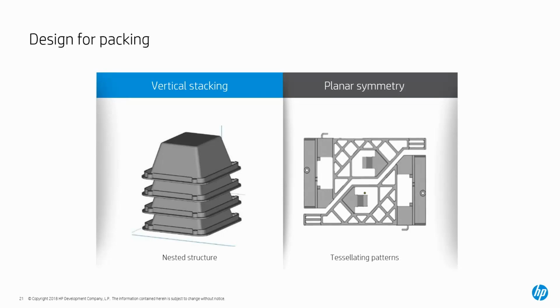in addition to the fact that it allows you to nest a little bit better inside the parts. One other process that we used was vertical stacking, or solo cupping. So typically this filter housing that you would see on the left-hand side would probably have 90-degree walls, but when you start to think about the strategy of how many parts can I fit in, do the parts need to have 90-degree angles in order to be efficient for the process of the end result product? We found that we could angle the walls of these parts a few degrees in order to fit more inside of the build envelope, in addition to getting the same properties that we needed for the final part, which allowed us to have more parts inside of the set.